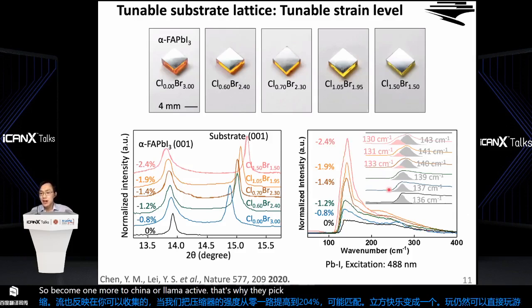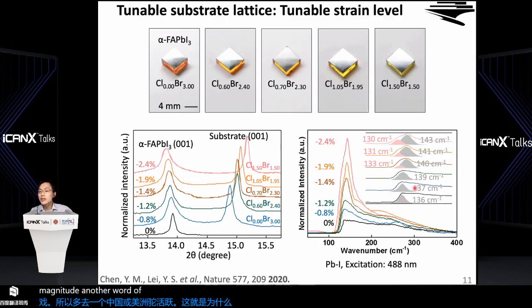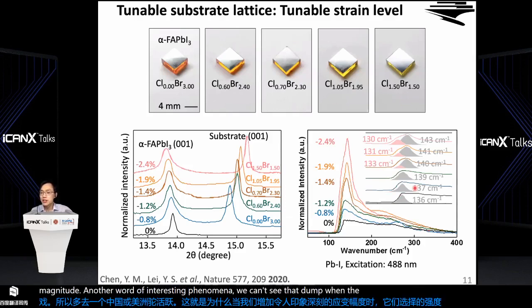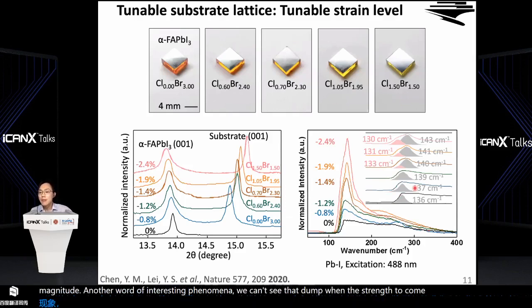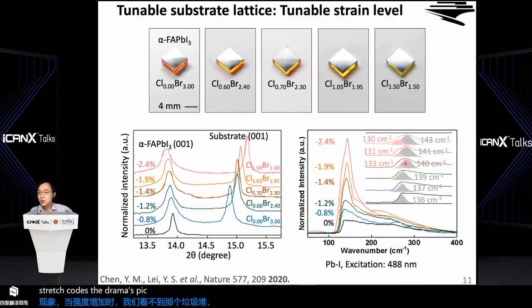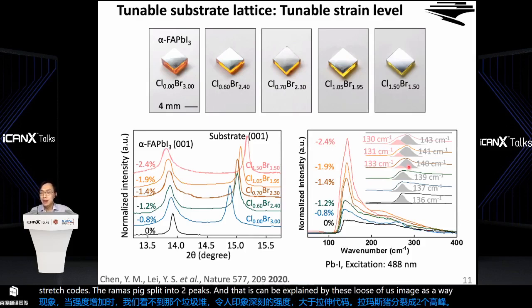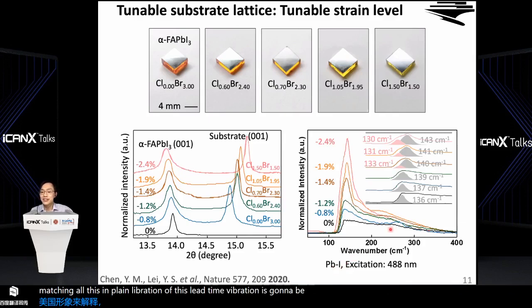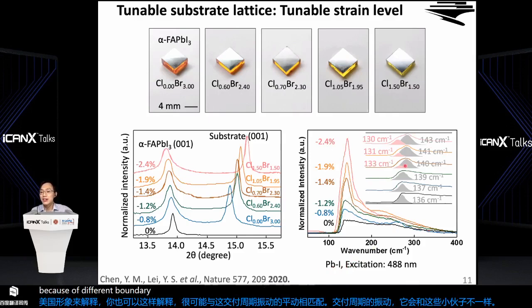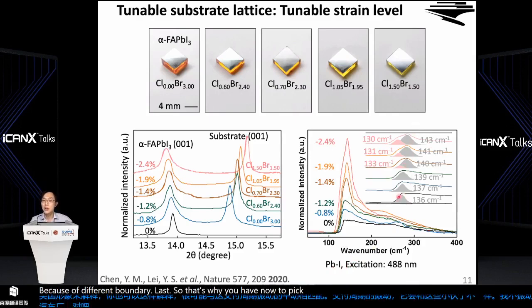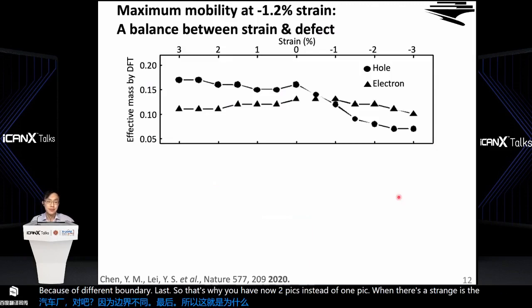Another very interesting phenomenon we can see is that when the compressive strain is larger than a threshold, the Raman peak splits into two peaks. And that can be explained by this loss of symmetry as well. As you can probably imagine, this in-plane lead-iodine vibration is going to be different from this lead-iodine vibration out-of-plane, right? Because of different bond lengths. So that's why you have now two peaks instead of one peak when this strain is becoming larger.